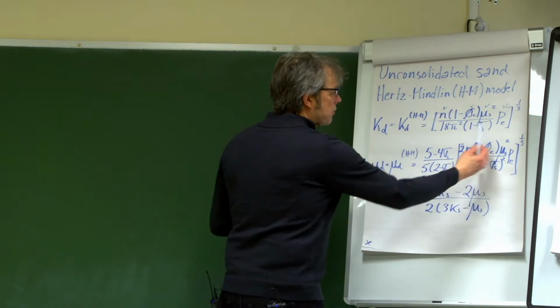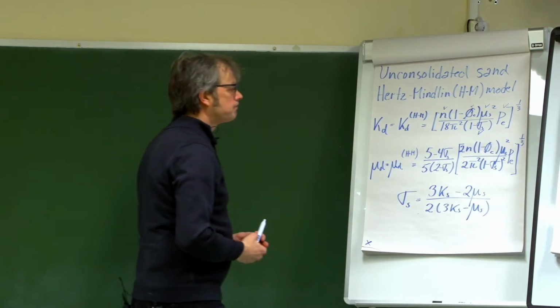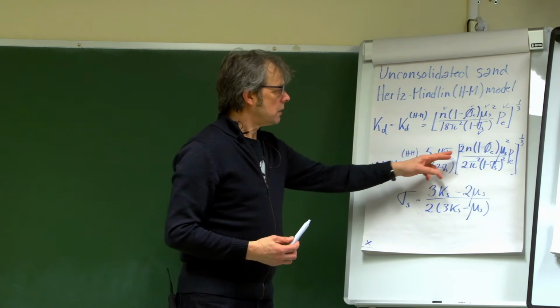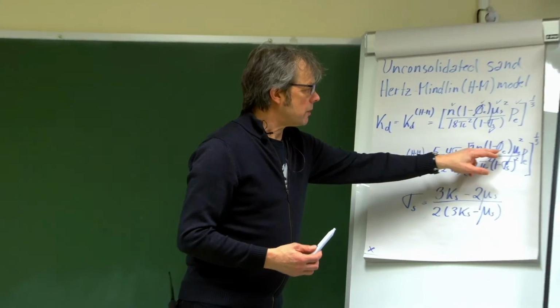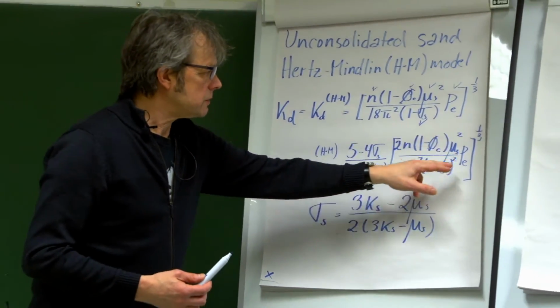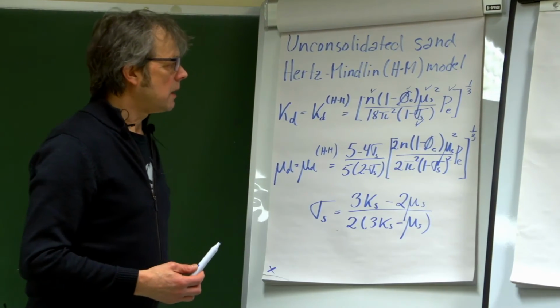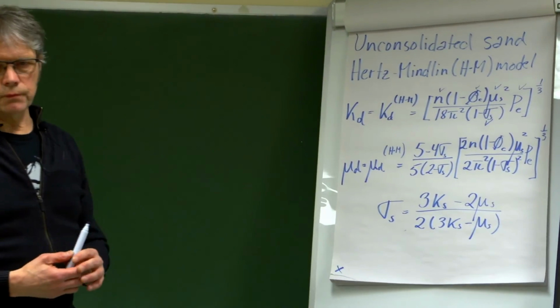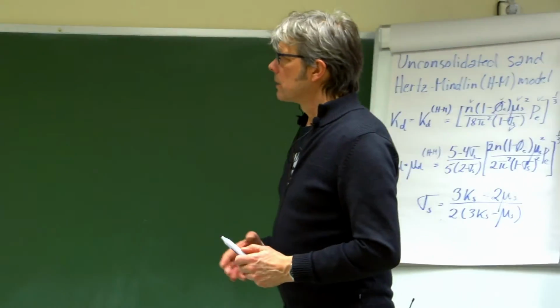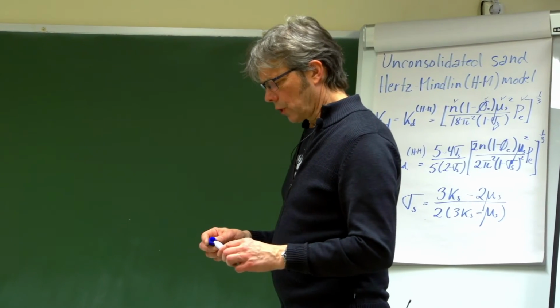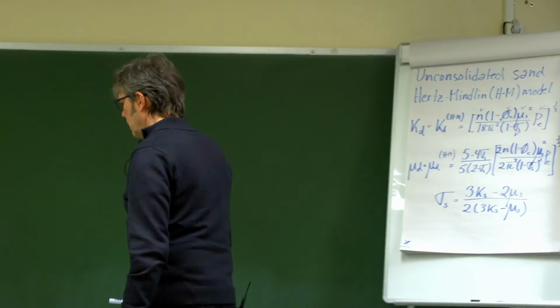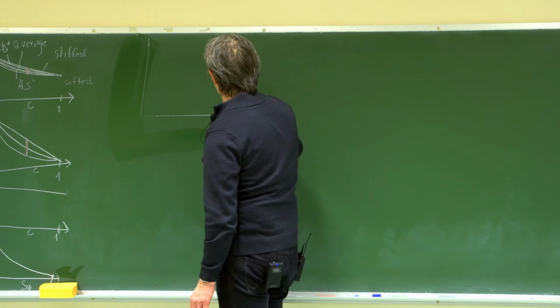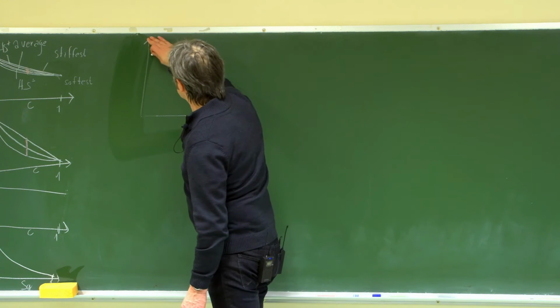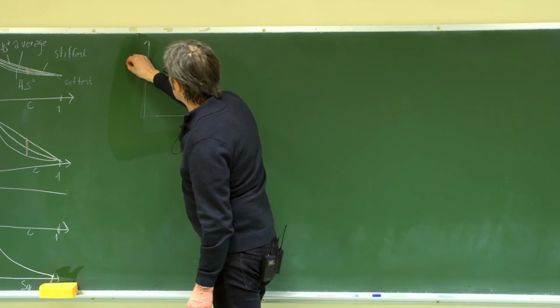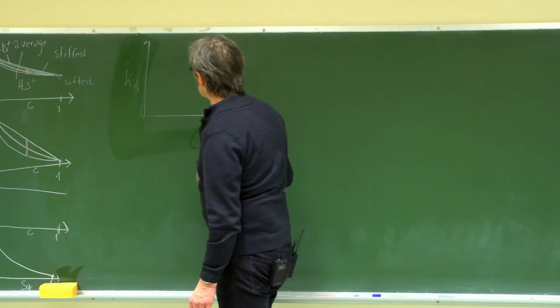And we see it's the same parameters that we have over here for the shear modulus: coordination number, porosity, shear modulus of the grains, Poisson ratio of the grains, and effective pressure. So it's just two formulas. Now I would like to make a plot of what I know up to now. I have the bulk modulus here, dry bulk modulus versus porosity.